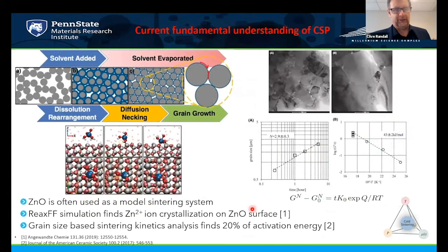So essentially what is happening is we use a transient phase that's going to aid the transport. So it's all about a surface chemistry and a surface additive, let's say, for example, water, or acetic acid in the case of zinc oxide, which is the case here. So you use basically an aqueous acetic acid mixture.